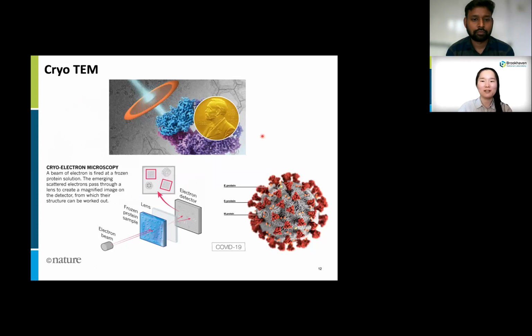Cryo-TEM is an interesting field, especially during the pandemic, because with this technique, coronavirus can be imaged. Cryo-EM is very popular in structural biology, but battery people are also interested in this technique because with cryo-EM, we can image electron beam sensitive materials like lithium metal. In general, liquid nitrogen is used to cool down the sample, but in some cases, liquid helium is also used, which can reach much lower temperatures. And this is really good for studying specific physical phenomena at extremely low temperature.